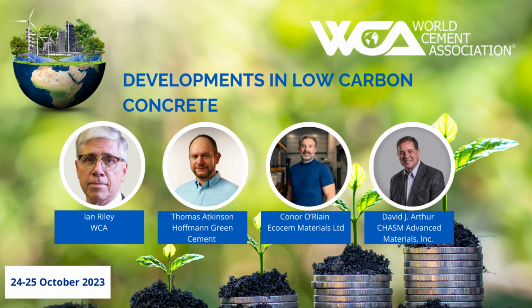I think we're all aware of this, and the presentations over the past few days have cemented this in my mind. Sorry about the pun. Now, as I said, concrete is not the problem, and in fact, cement is not really the problem either. We can make cement today. My colleague from Hoffman just described cement that has virtually no traditional cement in it. The source of the problem is clinker. The easiest and fastest way to decarbonize the cement industry is to minimize the amount of clinker per ton of cement and therefore per cubic meter of concrete.